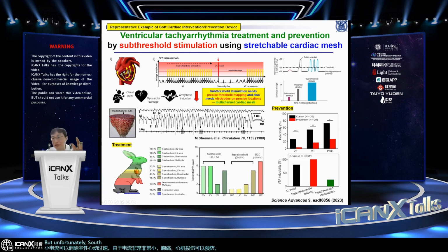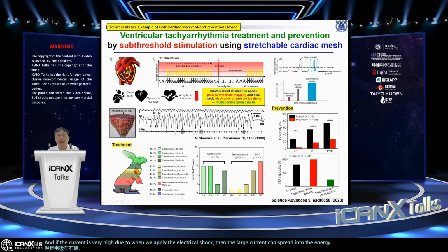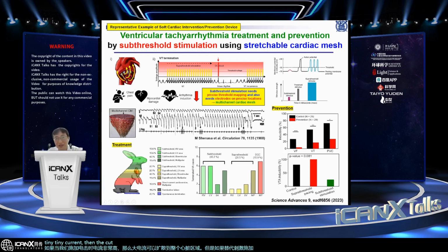But unfortunately, subthreshold stimulation could not be commercialized. Why? Usually VT occurs on the left ventricle, but the electrode is on the right side. If the current is very high, as when we apply the electrical shock, then the large current can spread into the entire heart region. But if the subthreshold stimulation applies a tiny current, then the current level is too small and remains only in a local region. That means with a single electrode, there is no way to apply subthreshold stimulation, especially for the left ventricle region.